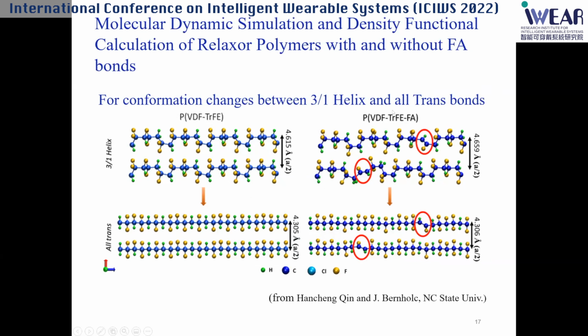For example, this is the PVDF copolymer without FA, in the 3-1 helix. This basically is a polymer conformation which is random, without polarization, without net polarization. And you can see, this is the one with the FA bond. And when we apply electric field, we can convert this 3-1 helix in a simulation into all-trans conformation.